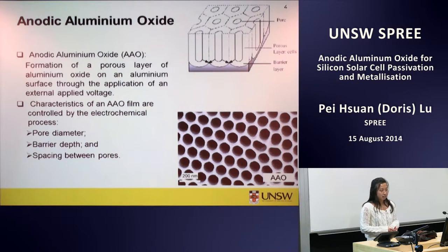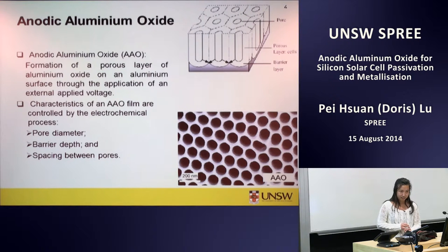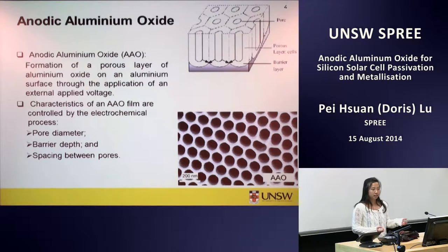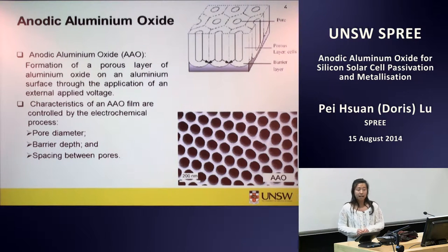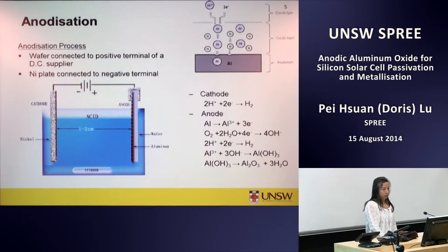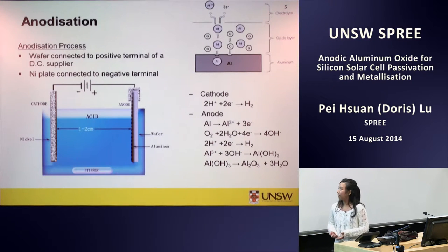Anodic aluminium oxide is a layer of aluminium anodized in acidic solution with an external electric field. The formation of a porous layer of aluminium oxide in acidic solution will result in a narrow pore structure. And this narrow pore structure can be controlled by voltage, concentration of electrolyte solution, and anodization time. Just a bit of background of how anodization